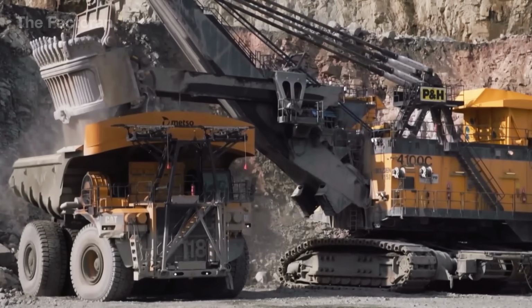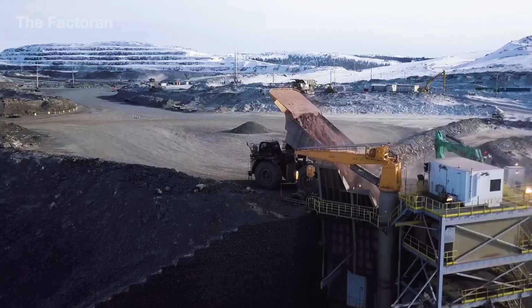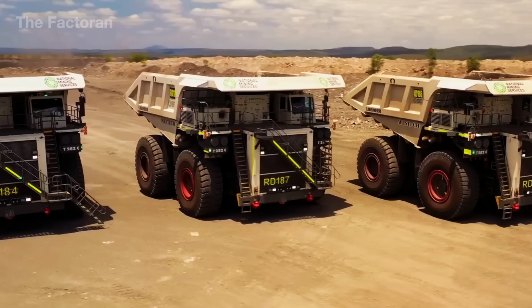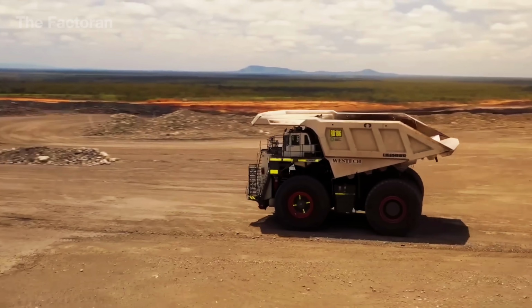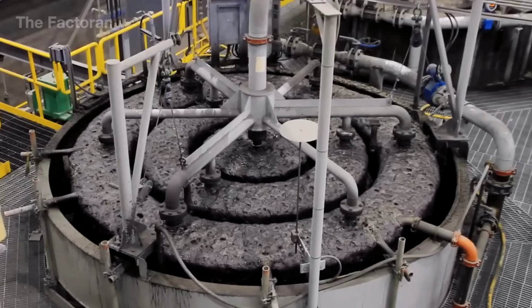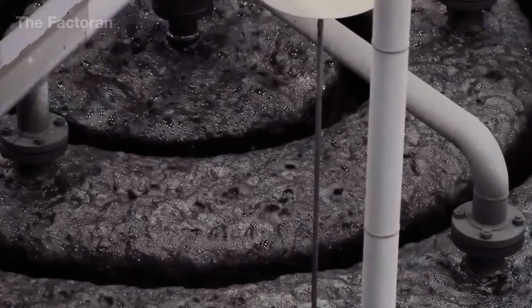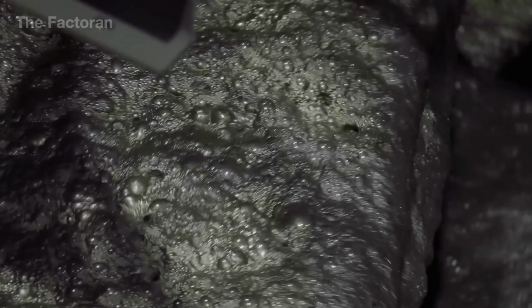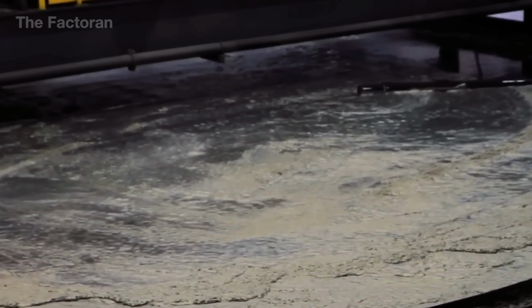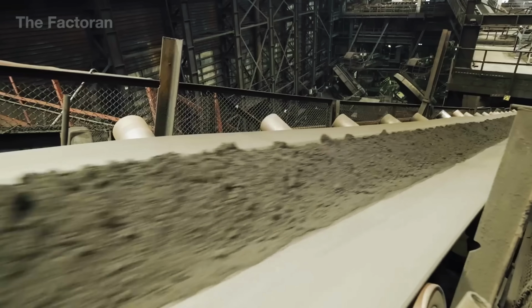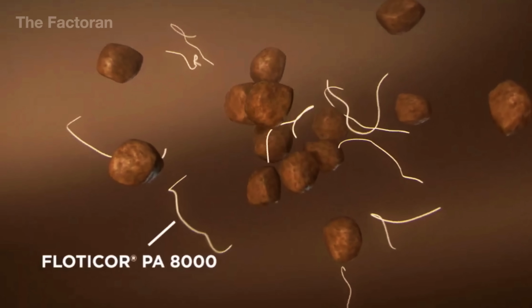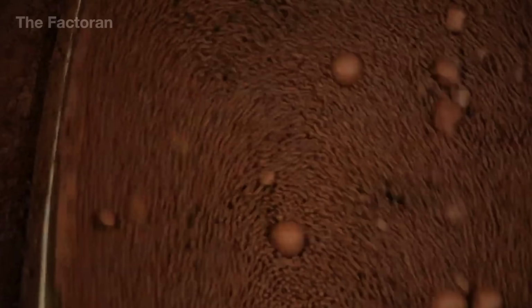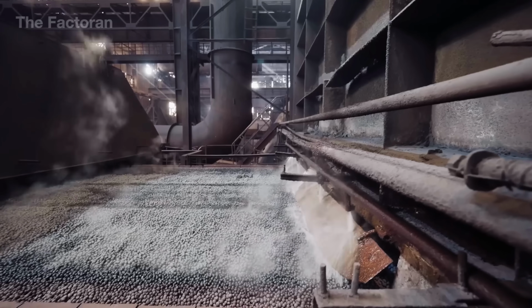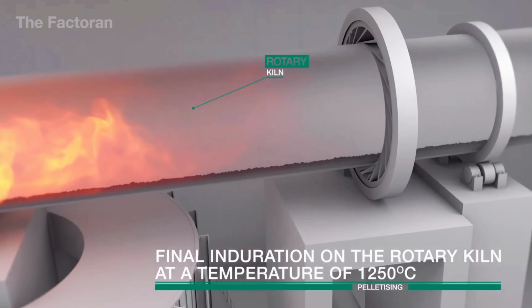Once mined, the raw ore is transported to processing plants. There, it is crushed by jaw crushers and ball mills, then screened to separate iron-rich particles from unwanted rock. Processing often includes magnetic separation, taking advantage of magnetite's natural magnetism, or flotation to improve the purity of hematite. For efficient smelting, the ore must reach an iron content above 60%, while impurities like silica, sulfur, and phosphorus are reduced to a minimum. Finally, the concentrated ore is agglomerated into small lumps through pelletizing or sintering, making it easier to feed into a blast furnace.